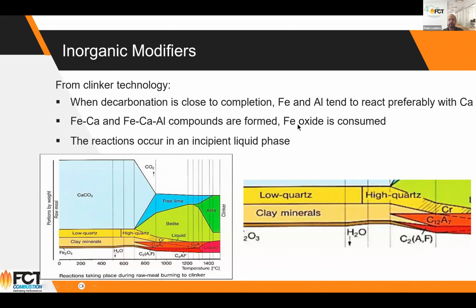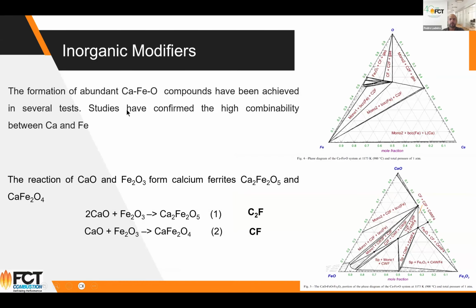So here's the key point. We want to get rid of the red color coming from the iron. So we should try to get as much as possible of this conversion, or consume this iron oxide. What we see is that once you get to a certain point, the system calcium iron oxide can be achieved in several tests. And we have confirmed this in many different ways, and we see this reaction going on. So as we add calcium to the clay, the iron reacts preferably with the calcium, forming this and forming this. Turns out that these compounds, the ferrites, are not red. They tend to be even green or black.